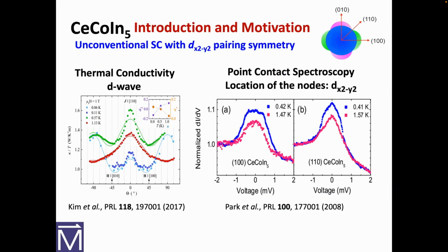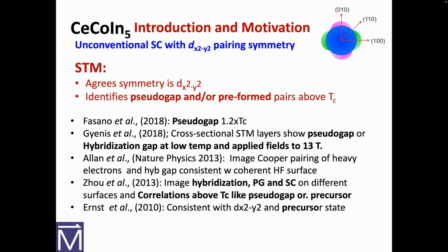And just to show you, it's been known for a long time. It's dx squared minus y squared. There was heat transport data that showed there were nodes. We did our point contact spectroscopy in about 2008, and we were able to show that where the nodes were was dx squared minus y squared. And basically everybody agrees with that.